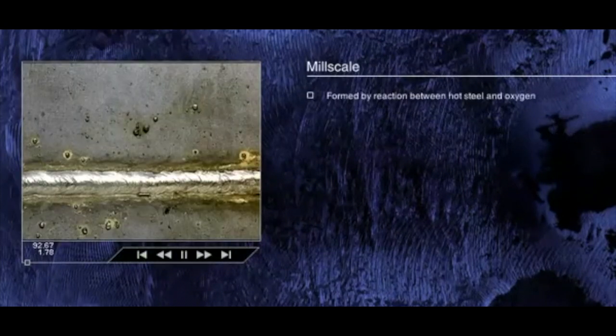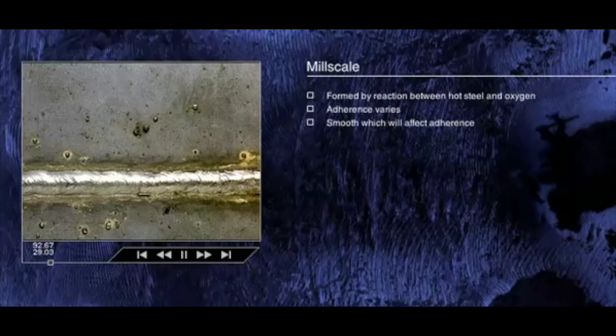Mill-scale is formed by reaction between the hot steel and oxygen in the environment during the production process. As a result, the surface of newly produced hot-rolled steel is generally covered with blue-black deposits of mill-scale. The adhesion of mill-scale to steel is unpredictable and may vary from tightly adherent to lightly adherent. If the mill-scale is over-coated, failure of the coating can occur due to delamination of the mill-scale from the steel surface.